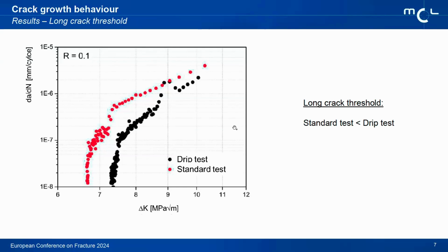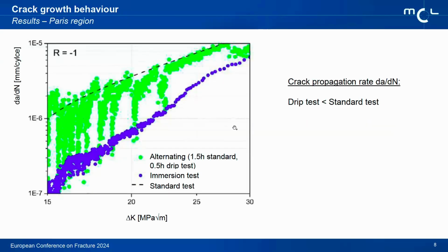Good. Then we had a look at the Paris region. So we moved from the load shedding method to the constant load delta K increasing method. And here the black dashed line is the fitted crack propagation rate for a standard test in ambient air. And first I want to draw your attention to the blue dots. These tests were performed with CT specimen. They were immersed in this corrosive fluid, and we received this crack propagation curve, significantly lower than the standard test. We compare with the dashed black line.